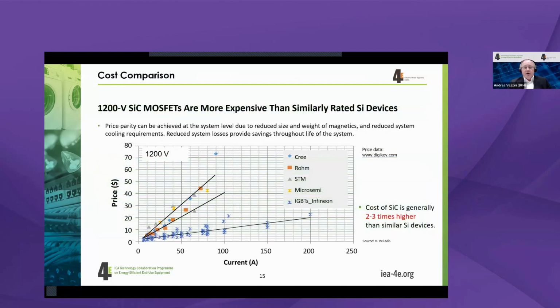And let me explain this a little bit more in detail by just showing you. If you look at 1200 volt power semiconductors, this line here, the blue one, is based on IGBTs from Infineon in that case. This is some cost comparison. You can see that with higher current density, there is more or less a linear relationship between the price as well as the current capacity. If you look now at the silicon carbide market with the 4 biggest competitors, there is a range there where you can see, which also allows a more or less linear approach. But what we see is basically that there is a price difference that easily can go from 2 to 3 times today, and on that slide might be even a little bit higher. So that's on the component or on the device sector.